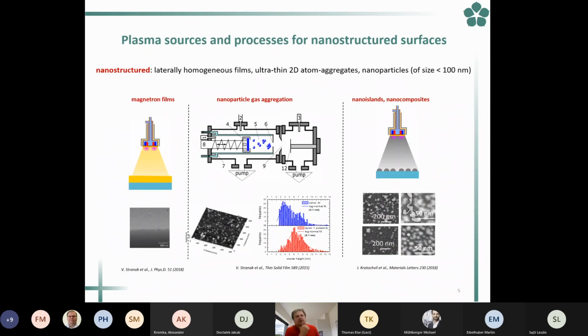The possibilities on our side are related to these techniques employing low temperature plasma. As you can see here, we are dealing with homogeneous thin films. Usually these are in the thickness of nanometers, maybe some hundreds of nanometers, usually not more than 1 micron. We can deposit various materials, starting from metals up to plasma polymers.